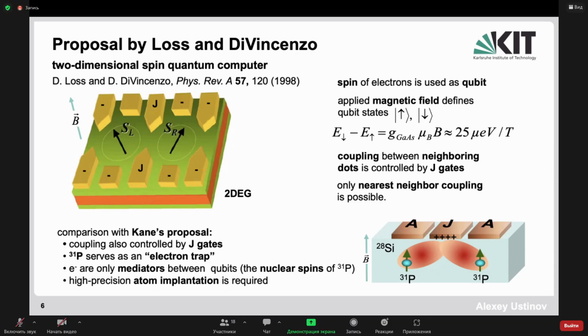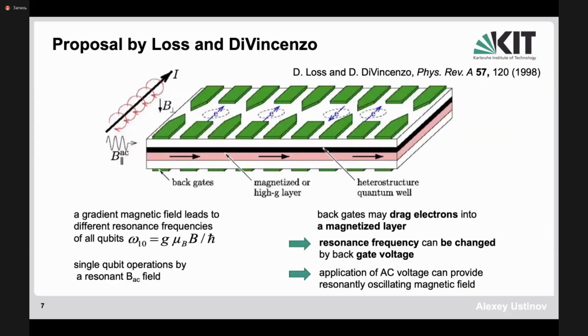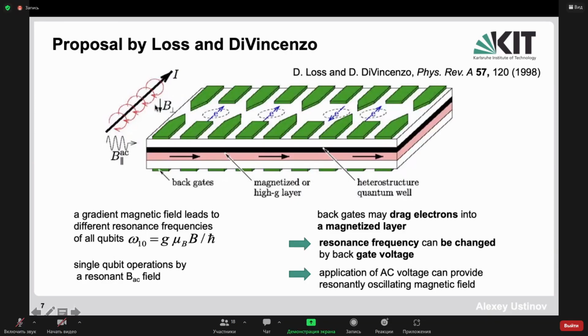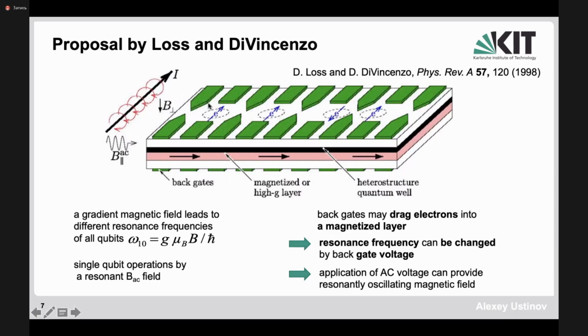Nevertheless, it was very hard and difficult to implement all the required steps for demonstrating quantum computing potential with these structures. So the initial proposal of Loss and DiVincenzo was considering using a wire as a source of magnetic field, and then the magnetic field decays away from the wire such that there will be different magnetic field magnitudes seen by the leftmost dot and then the other dots and so forth. So the magnetic field was decaying, and therefore the Zeeman splitting was decreasing from left to right. And therefore one can choose an individual resonance frequency for different dots, which are located at different distances from the current-carrying wire. And then one can apply the AC electromagnetic field to manipulate the quantum spin states of the dots due to the Zeeman splitting.